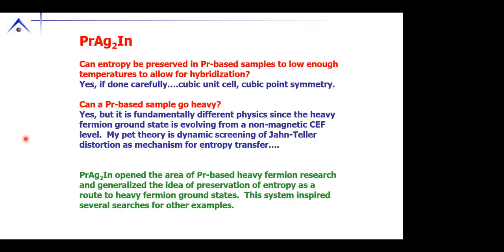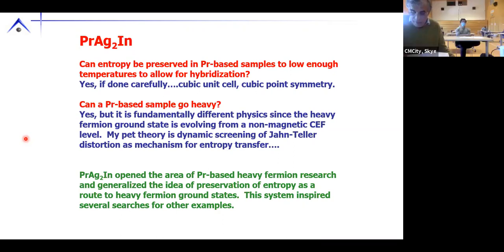Well, as I say, my experimentalist image of this is we're dynamically screening with the conduction electrons the predisposition to have a Jahn-Teller distortion. Okay, so if you want to say in a heavy fermion, you would look at the quasi-elastic line width. I think here, what you'd want to do is look at the phonon spectrum and see if something interesting is happening in the phonons as you go into this heavy state. Thank you. Yeah.